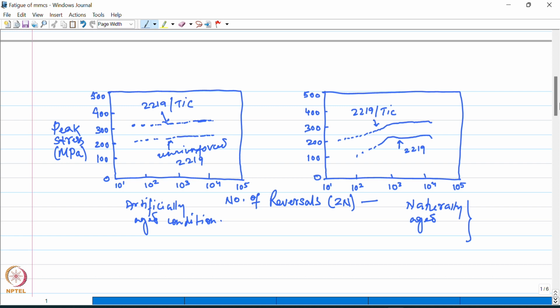Although the general response to cyclic loading could be the same for both the composite as well as the unreinforced matrix material, as you could see from here or here also. Only difference that you see due to the presence of the reinforcement particles is that the stresses are higher in the composite for a given amount of plastic strain.